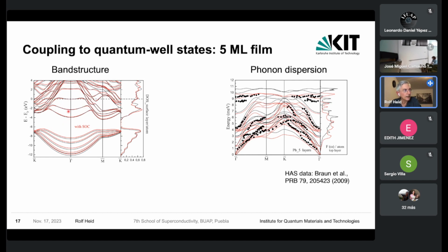And here we also see very nicely separate bands, which mimic the existence of these quantum well states at the gamma bar point. And in this case, you see one of these very flat bands close to the Fermi level, which leads to an increased density of states at the Fermi level. And that is of importance for the superconducting properties.